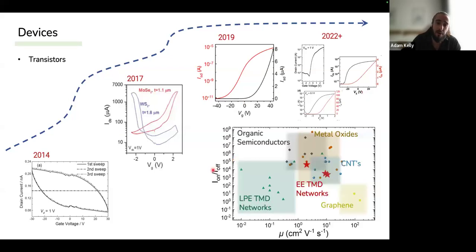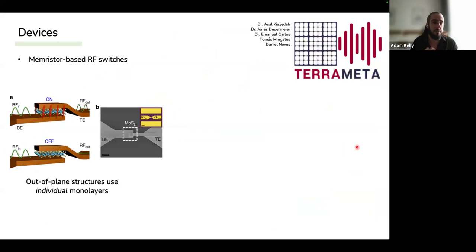So going back to this way of characterizing it, this on-off ratio versus the mobility, what we find is that the electrochemically exfoliated TMD networks, which are materials like MoS2, are now competitive with the commercially mature metal oxides and carbon nanotubes. What's important to note too is that metal oxides and carbon nanotubes tend to be reaching a ceiling on their performance. And with 2D materials, there's a lot of scope to go much, much further. It's not going to be long now, I think, until we see a mobility of about 100 in some of these networks.